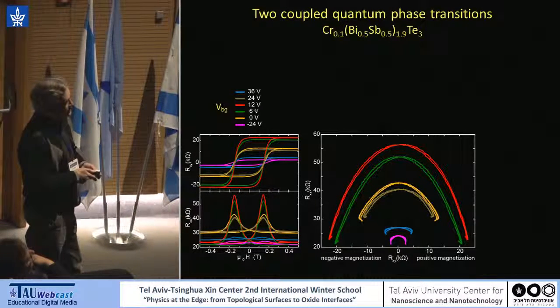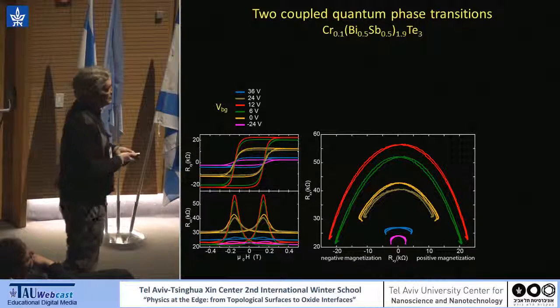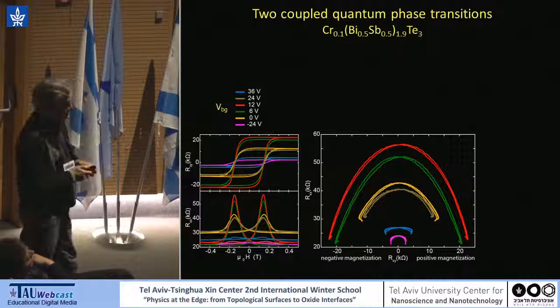And you can see, for example, that Rxy goes from negative value to positive value. So this is going through this plateau transition where Rxx peaks and goes down. So this is the arc. And essentially, the plateau values are just the endpoints of these arcs. So actually, most of the data here is what happens in the transition. So this gives us a very easy handle to separate the two systems.